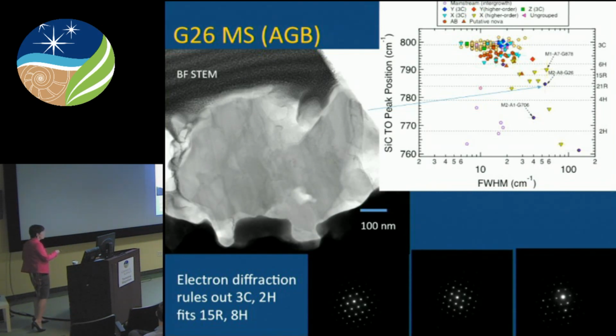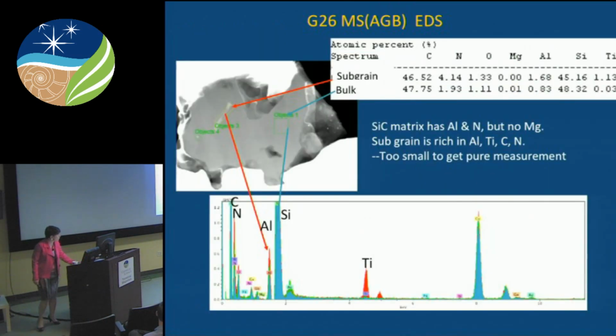And by obtaining 3 separate electron diffraction patterns at different crystallographic orientations, or zone axes, different tilts of the crystal, I could rule out both those low temperature polytypes. It's not 3C or 2H. It best fits, according to my calculations, to the 15R rhombohedral, although I can find an alternate indexing to the 8H crystal structure as well. So lo and behold, nature does make more than the low temperature polytypes.